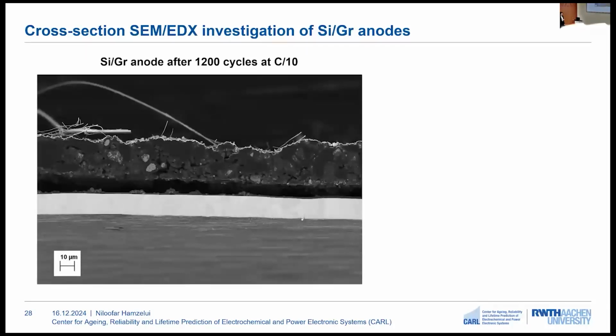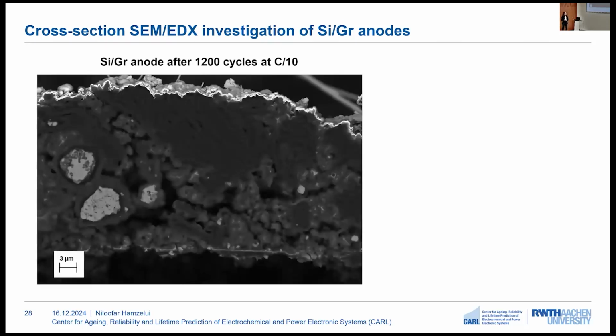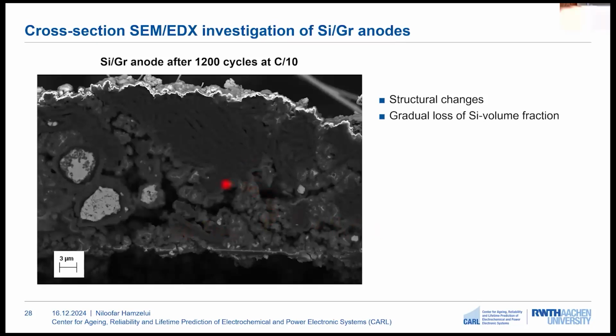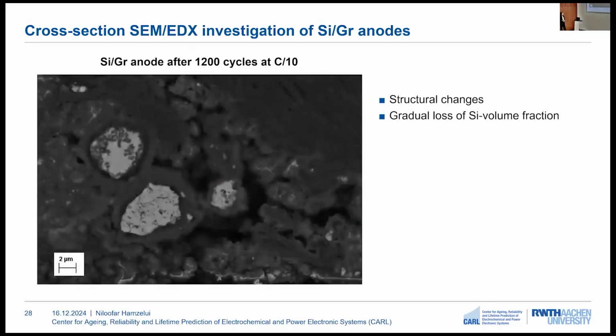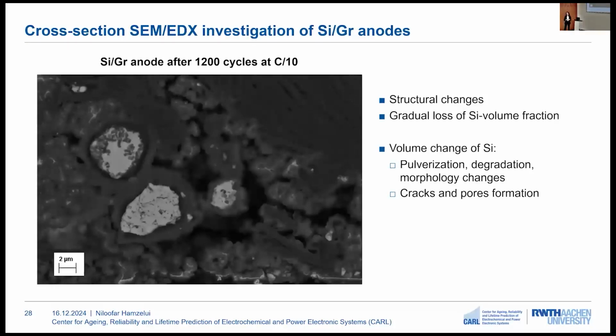After almost 1,200 cycles, the cells were disassembled, and again, the morphology of the electrodes was investigated using SEM and EDX. Here we can see a cross-section SEM image of the electrode after electrochemical cycling. And if we further zoom in, we can better see the structural changes that happen in the electrode. Mostly we can see a gradual loss of silicon volume fraction, and this can be due to the volume change of silicon upon charge and discharge, which can result in more degradation, delamination of silicon particles, and formation of cracks and pores. In this image, we can also see different stages of silicon degradation.